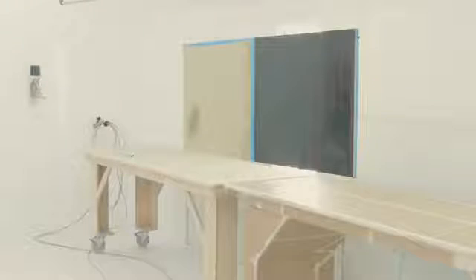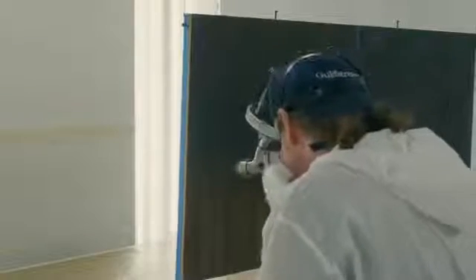To finish new veneer cabinetry, first apply a light coating of Blue Sky Armor 1007 sealer on the veneer. After allowing the sealer to penetrate the veneer, a second and perhaps third mist coat application of Blue Sky Armor 1007 is applied to assure complete saturation of the veneer.